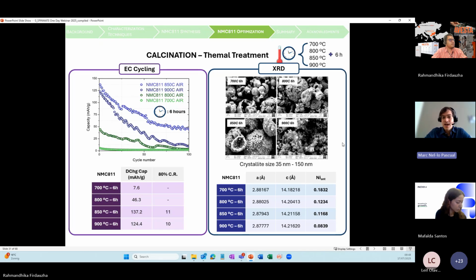We can see that at 700 and 800 degrees, you can see the secondary particles of the materials, which are round or spherical-shaped particles that are hollow inside, but at these magnifications, you cannot see the primary particles. In the case of the 850 and 900, you can see the primary particles that are much larger. And with the refinement that I was mentioning, you can obtain the crystallite size, and you can see that for the lower temperature ones, the crystallite size was around 30 nanometers, and by increasing the temperature, you increase this crystallite size up to 150 nanometers.